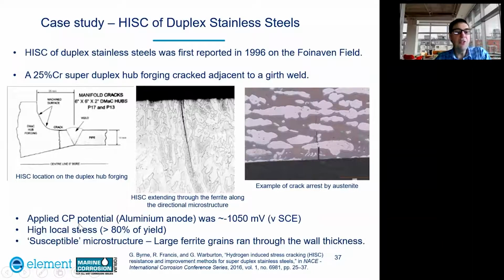So the applied CP potential, which was applied using a sacrificial aluminium anode, was at minus 1050 millivolts, which resulted in an excess amount of hydrogen being generated. In addition to that, there's high local stresses, which were above 80% of the yield, and a susceptible microstructure where you had large ferrite grains which ran through the wall thickness of this hub.